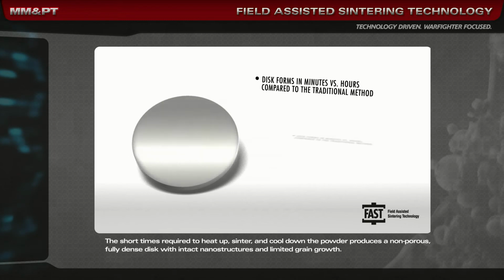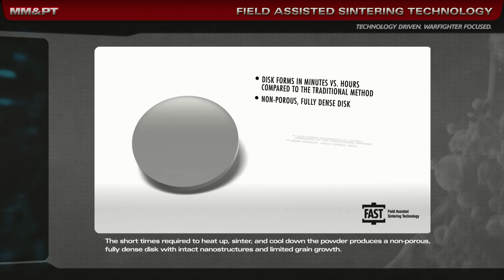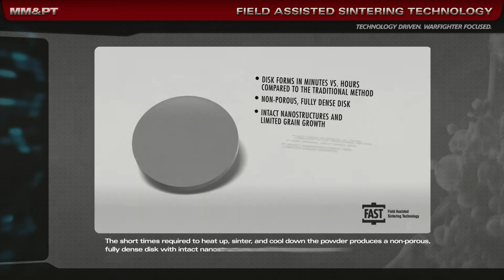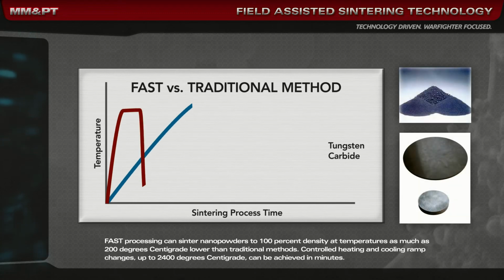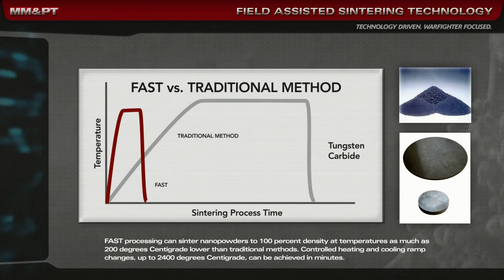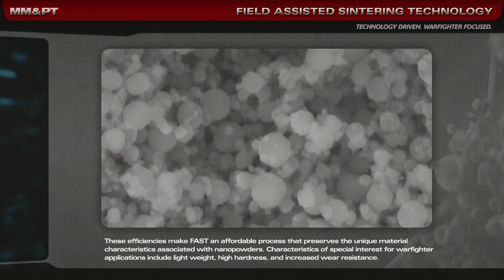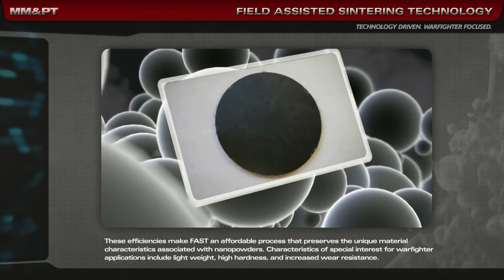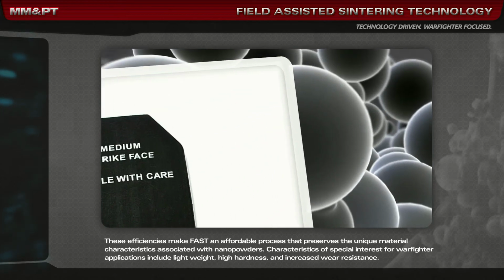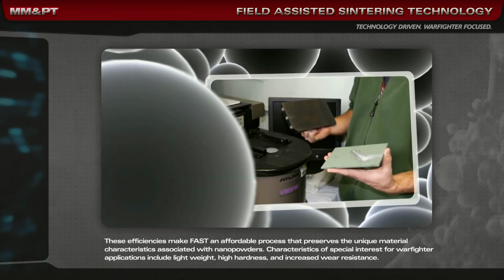The short times required to heat up, sinter, and cool down the powder produces a non-porous, fully dense disc with intact nanostructures and limited grain growth. FAST processing can sinter nanopowders to 100% density at temperatures as much as 200 degrees centigrade lower than traditional methods. Controlled heating and cooling ramp changes, up to 2400 degrees centigrade, can be achieved in minutes. These efficiencies make FAST an affordable process that preserves the unique material characteristics associated with nanopowders.